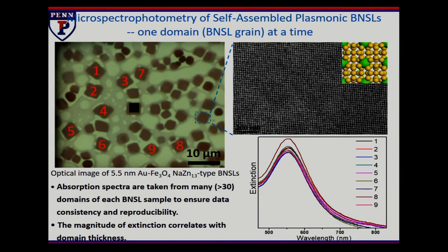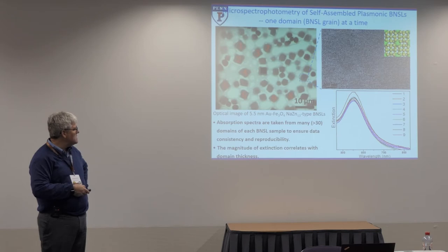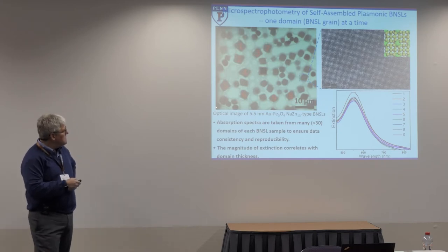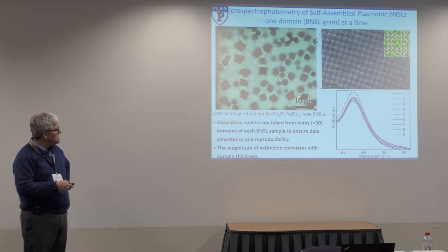Let's put plasmonics together. So when you start to design systems that have combinations of interactions, one of the things that we were talking about before was the ability to make this connection between single molecule type spectroscopy, individual structures, and what's the property of the extended film. And so this kind of experiment, where we look very early in the nucleation of one of these superlattices, offers us an opportunity where we can map one-to-one structure onto, in this case, optical function. So this is just after the nucleation of a series of these islands, and with more material, they would grow out to begin to connect to each other, and everywhere that there's a misoriented island would ultimately have some type of a grain boundary.